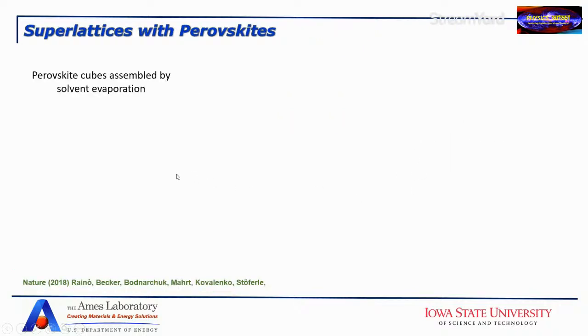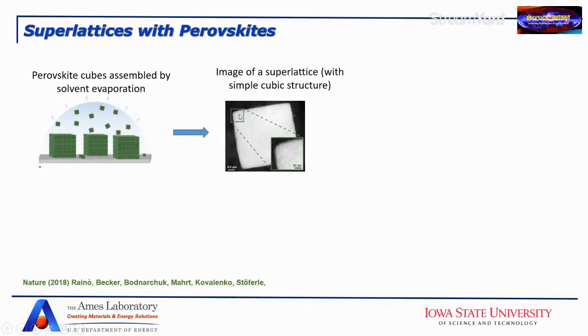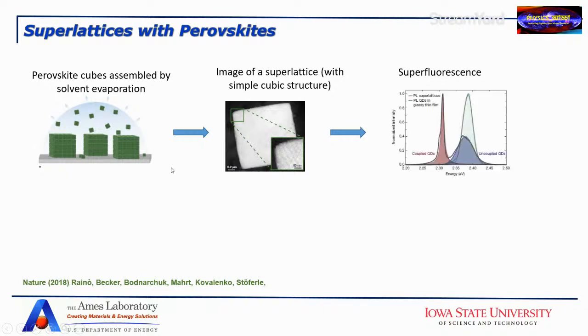And one important success was when this group here, which I collaborated with about 3 years ago, was able to make cubes by solvent evaporation. So they put the cubes here, here you have the solvent, they evaporated the solvent, and they found what you can see here, these huge superlattices which have cubic structure. When you magnify this corner, you can still see the single cubes that are formed there. And one thing that happened is that, surprisingly, these materials exhibit a property which is called superfluorescence.